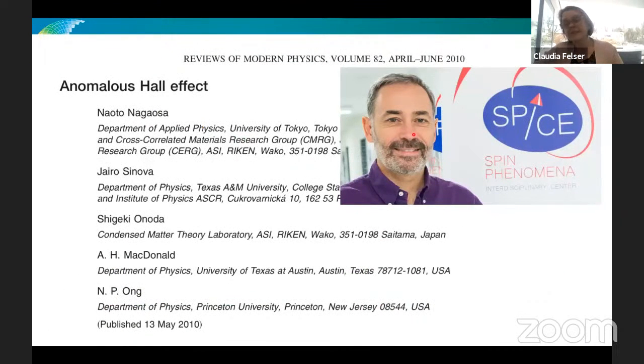And the anomalous Hall effect, I think we have very nice reviews. So this is like in 2010, in this nice review with Nagaosa, Sinova, MacDonald, Ong, and Onoda, it was already described that the Hall effect goes with the Berry curvature. And thanks to my collaboration with Jürgen Kübler, he was already early interested in the Berry curvature. So we calculated also for many of the Heusler compounds the anomalous Hall effect based on the Berry curvature. So this also explains the anomalous Hall effect in this non-collinear antiferromagnetic material, because they have a Berry curvature despite having a zero magnetic moment.